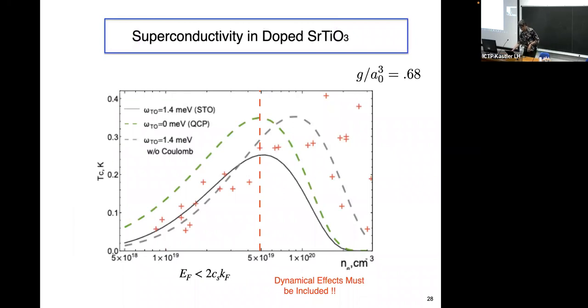Okay, so our maximum, just to say, so what do we have here? Okay, we have strontium ruthenate again. It's not strontium ruthenate. I was listening to your talk. Strontium titanate. There's a strontium there and an oxygen. Strontium titanate. What do we have here? Well, the red points are data. The black points are what is our fit to that. We use G over A0 cubed to be 0.7. That's important because that coupling constant is very similar. That's why it has to be in the log. The coupling constant is very similar to what was used by Dmitry and Abhishek and also by the other one. We'll talk about that in a minute.